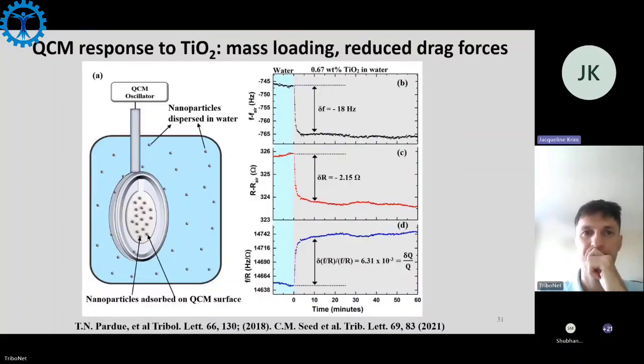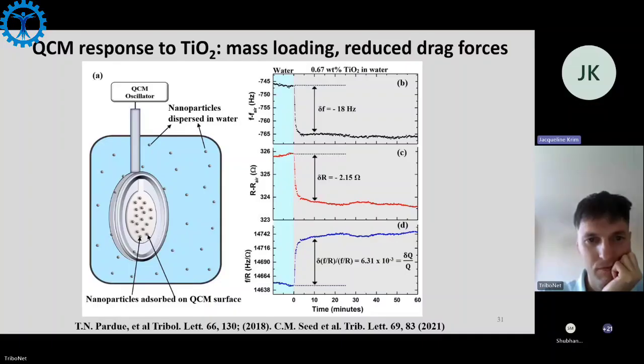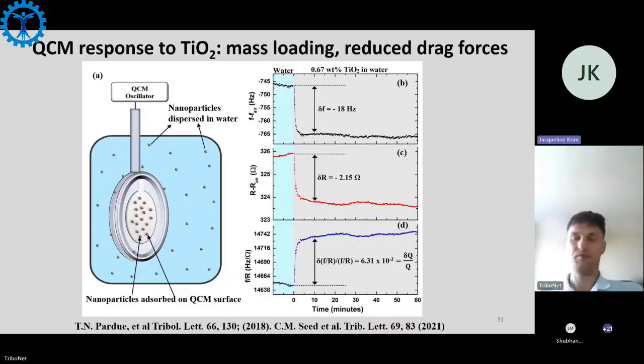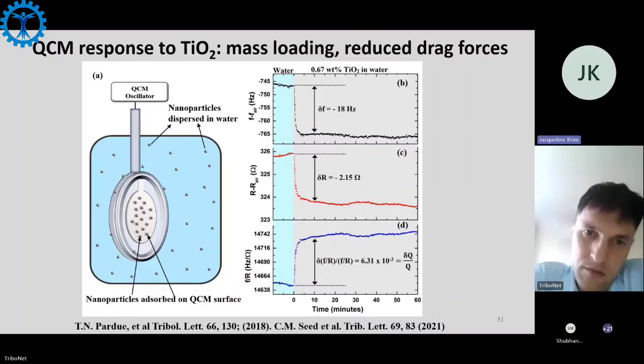So here's an example of these drag forces going down. As a function of time, we've dipped, say, in this case, platinum QCM into water, and that was the left-hand blue area. We add 0.67% titanium oxide particles. Those were 40 nanometer. We see a drop in the frequency, but not as much as would be expected for the increased density of that liquid. And more remarkably, we see a drop in the resistance to motion, even though it's a more viscous material. So you would think that the drag forces would increase if you're putting your hand like through thicker material, but in this case, they actually decrease due to the presence of the titanium.